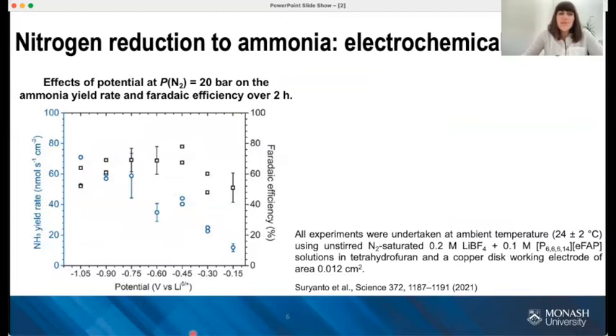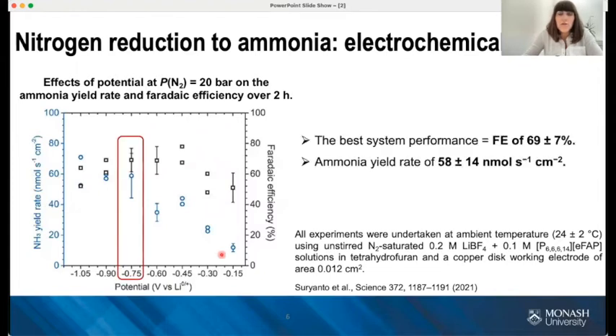So in the next step, we used this phosphonium proton shuttle in the nitrogen electroreduction process. Cyclic voltammetric analysis demonstrated that the reduction of lithium ions in the presence of the phosphonium cation is highly efficient. As you can see here in the figure, we tested a range of potentials, and in each case we produced ammonia. The best results we obtained at minus 0.75 volts, and that gave a Faraday efficiency of around 70% and a high ammonia yield rate of 58 nanomoles per second per centimeter square.